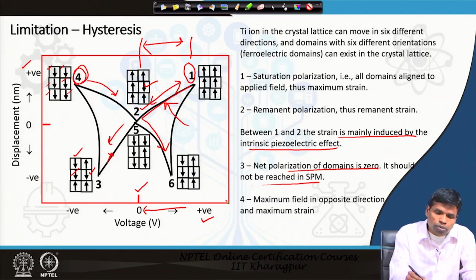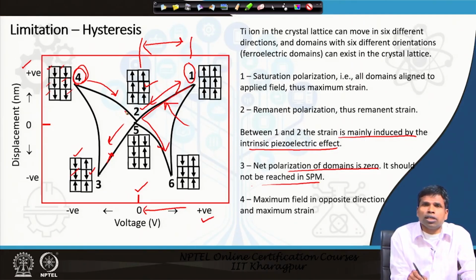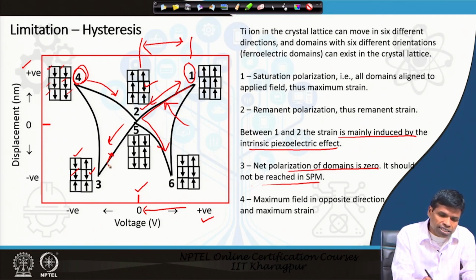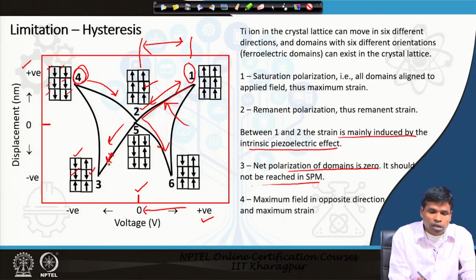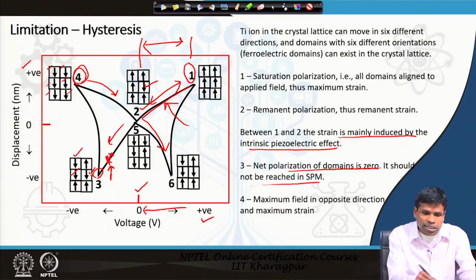So, the working range of the unipolar operation is between 1 to 2, and for the bipolar operation that we have seen in our piezoelectric tube, that is what is used in STM, we should not reach 3, but stay before that. So, operation has to be done up to a potential below 3, because at 3 there is a complete depolarization of the system. So, this is the hysteresis, because they do not follow the same path, a butterfly type of curve.